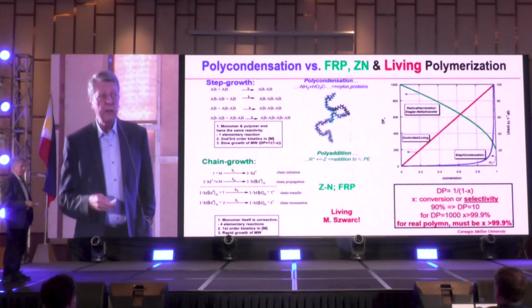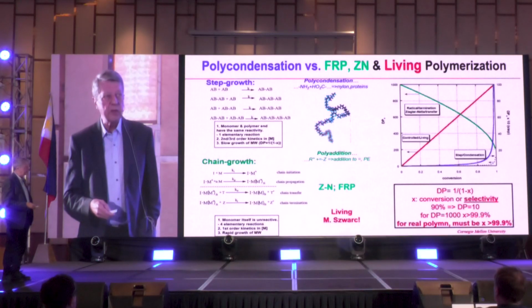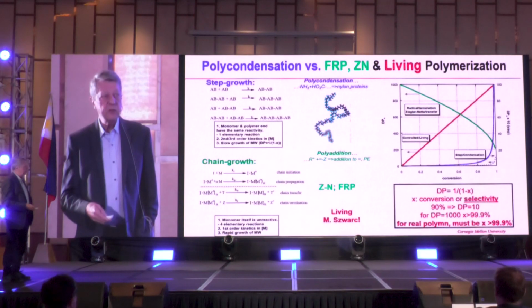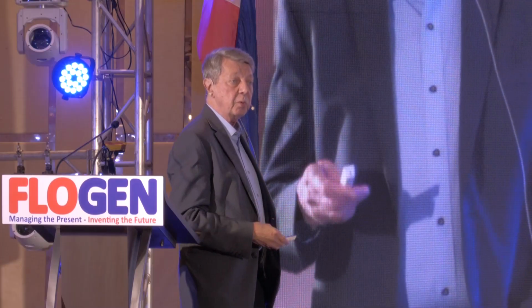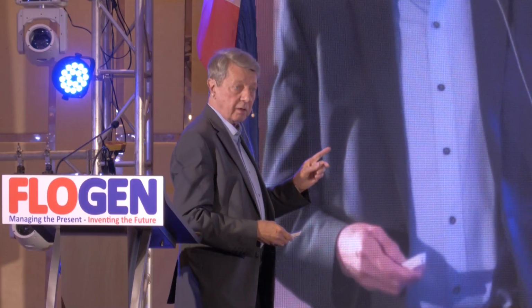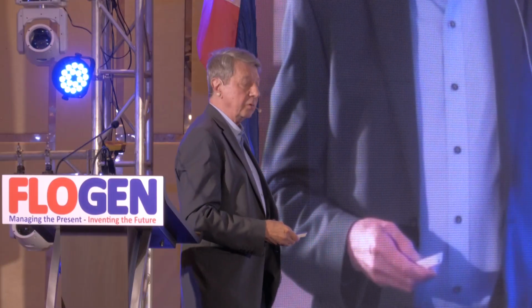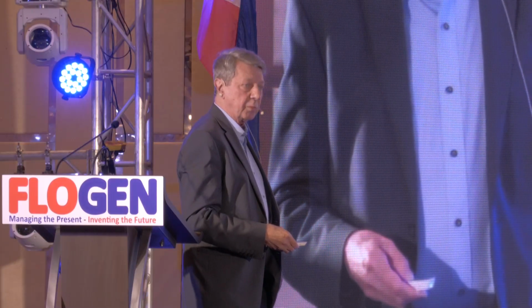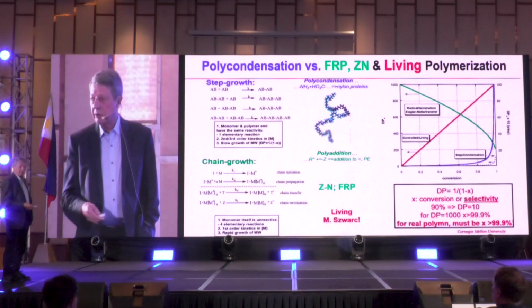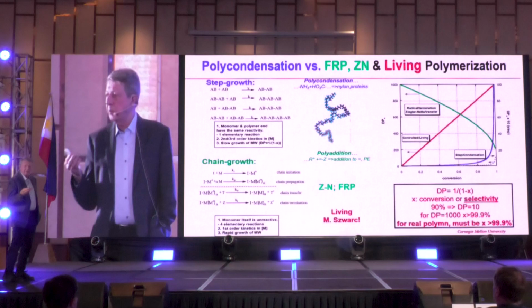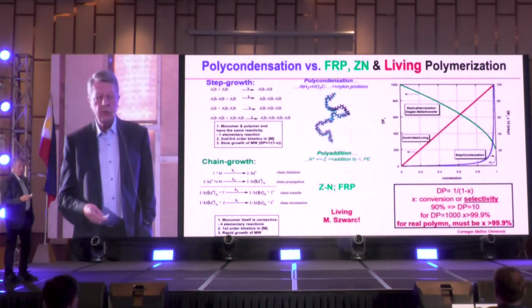Because of that, the molecular weight or degree of polymerization increases very slowly with conversion. It follows the so-called Carothers equation, and this X means conversion. So if you go to 50% conversion, you get only dimer. If you go to 90% conversion, this X would be 0.9, you will get a decamer. So in order to get a polymer with degree of polymerization, roughly speaking, 100, you need to go to 99% conversion. This is a challenge. It takes time, it takes energy. So how else can we make polymers?